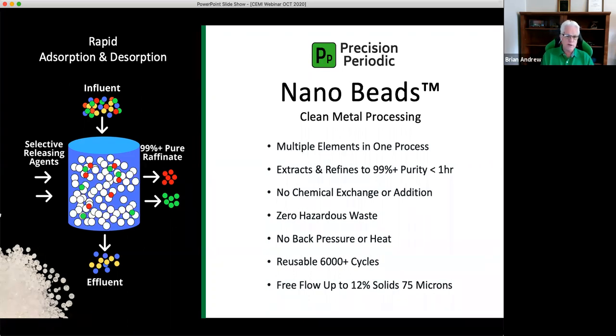And so this process is very fast. The absorption kinetics and the desorption kinetics are in minutes, not hours or days or weeks. It's actually quite amazing to watch how fast it is. And the beauty of speed is that your work in progress can be very small. So if you're processing 1,000 tons an hour of ore, you're only storing 30 minutes of the PLS before you can reuse it. All your tanks and everything you've got are much smaller and much more cost effective. And of course, you're not producing millions of gallons of waste. So that's the basic theory, the basic action of the way this filter works.